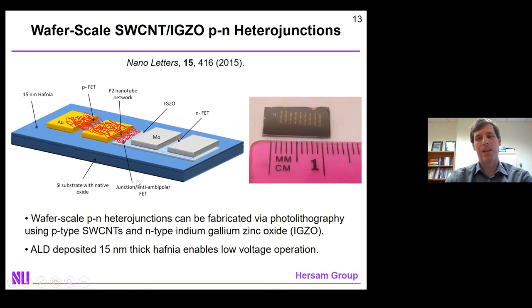And so we had to switch away from MoS2, and in particular, we went to another N-type semiconductor, namely indium gallium zinc oxide, which you can easily process at wafer scale. Semiconducting carbon nanotube networks can also be processed at wafer scale. And that allowed us to achieve anti-ambipolar heterojunctions at wafer scale, where we were more careful with the dielectric. We made it thinner and higher K, and that allowed us to also lower the operating voltages of these devices.